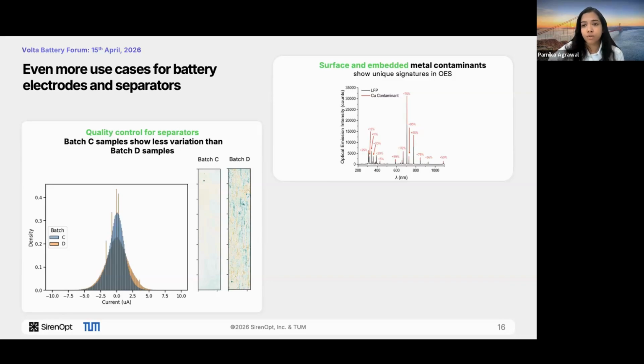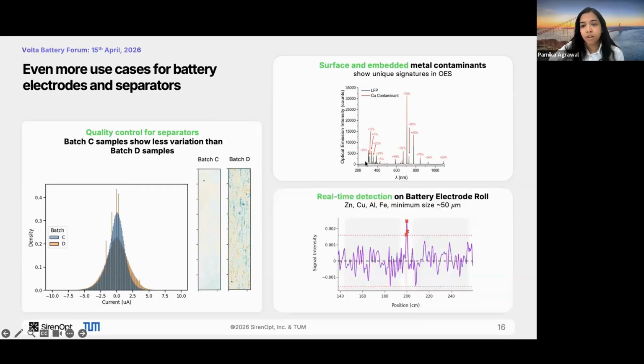The image here shows how our optical emission spectrometer data changes when a copper contaminant is detected on an LFP cathode. We are employing this now for real-time detection on battery electrodes for four different kinds of metal contaminants: zinc, copper, aluminum, and iron. Roughly, the minimum size we're trying to detect is 50 microns. This is real data from our tool, showing how these outliers show up as a deviation from the baseline signal. We have different models for each metal contaminant type, so we can identify the contaminant and pinpoint its location in the electrode.